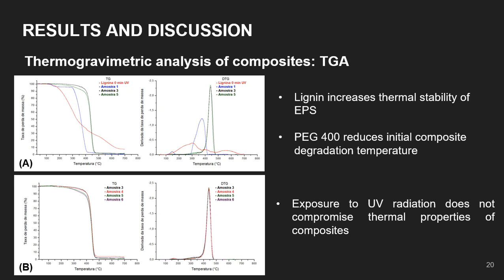Regarding the photochemical treatment, this again meets what was observed in the FTIR, since the TGAs showed a slight reduction in the degradation temperature of samples 4 and 6 in comparison to their analogs without exposure to UV radiation. However, this does not compromise the thermal properties of the composite, since this phenomenon occurs at initial temperatures of degradation.